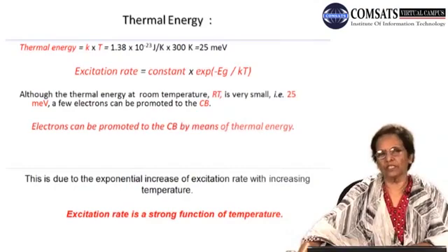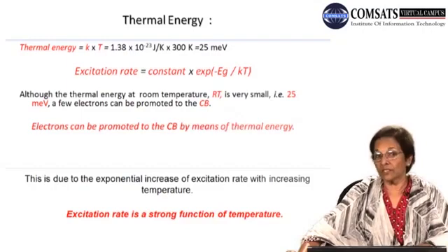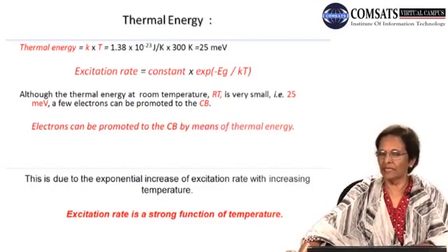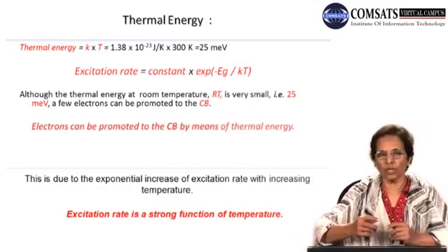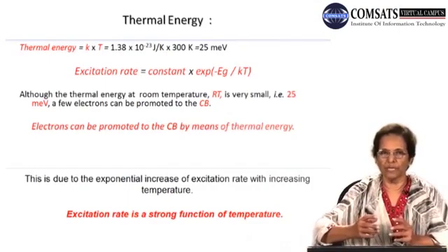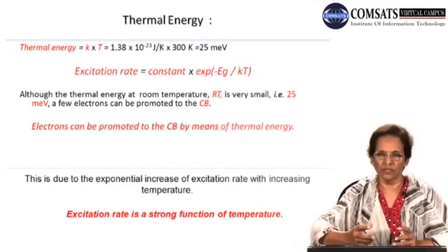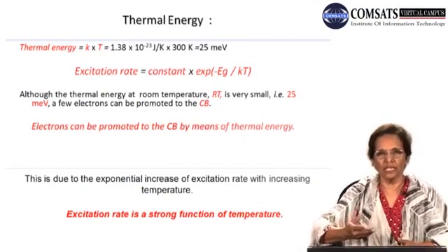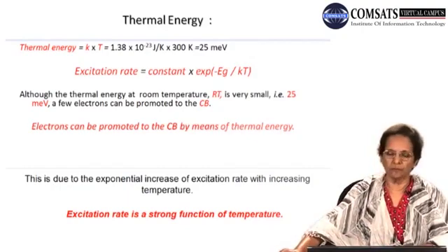This process is termed thermal generation of electrons as well as holes, and as I had written at the bottom of my slide, this thermal excitation or thermal generation mechanism is highly temperature dependent. As you increase the temperature, more and more bonds will be excited and broken in a given silicon material, and hence an enhanced thermal generation concentration will come into being.